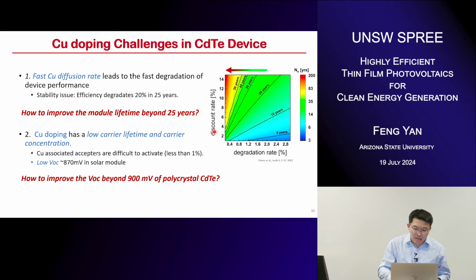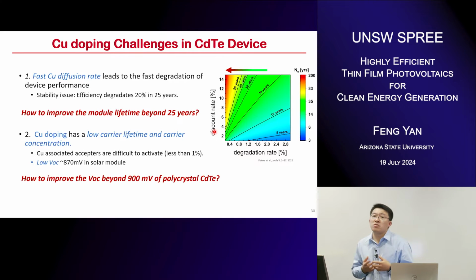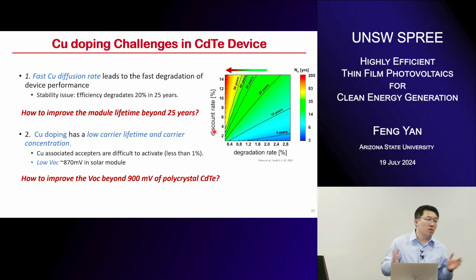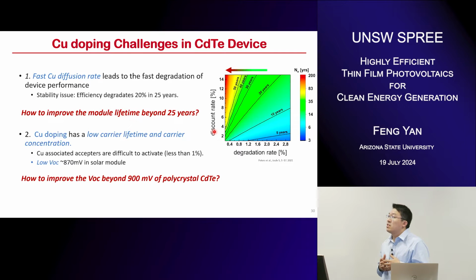But this technique has several defects. For example, the copper diffusion will lead to degradation of the module or the solar panel. And the module lifetime is around 25 years, which will degrade around 20% of the efficiency. How do we extend this module lifetime from 25 years to 50 years? So then you don't need to replace the module in the field, right? Particularly for utility-level PV, this is very promising for the power company.